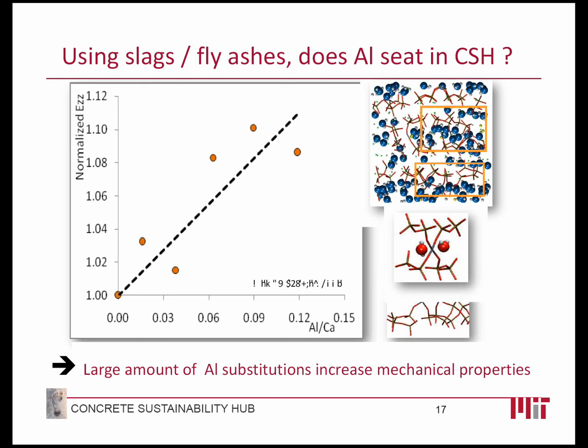This addresses aluminum substitutions in the context of using slags and fly ashes. On this plot, you can see the elastic modulus of CSH as a function of the aluminum over calcium ratio, and this is an increasing function. We found that if we use a large amount of aluminum, substituting some of the weak or defective calcium sites, we can accommodate quite a large amount of aluminum, and that actually benefits the structure because it improves its mechanical properties.